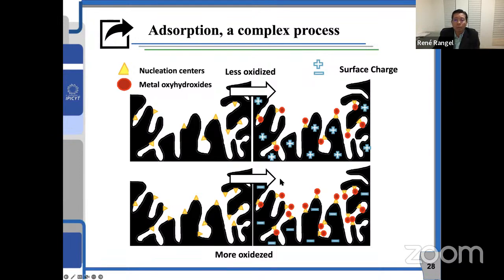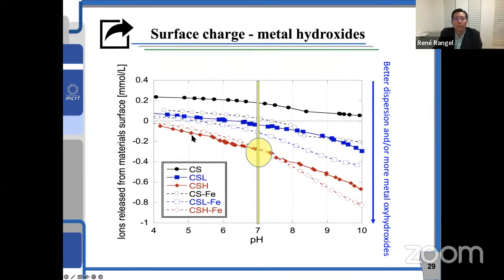The answer is that if we oxidize the material, then we will include more metal oxides, but not all the oxygen-containing groups are capable of anchoring metal oxides. And let's say that these oxygen-containing groups that do not interact with the metal oxides will give us negative charge. And so, if we have again a material with a lot of metal oxide, this is the surface charge distribution. As you can see in this example, its surface is very negative, and that's not good for the sorption capacity. So we need to have a balance.